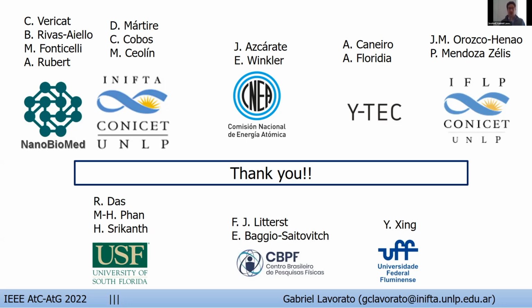So other options to use in the shell maybe are silica coatings, but silica coating has the problem that maybe it's difficult to control the porosity for these thin shells. So it is important to control the oxidation degree while preserving the biocompatibility. You can also try, for example, to use a ferrite shell, as in our case, without cobalt, to have a biocompatible shell, and this will be an intermediate solution.